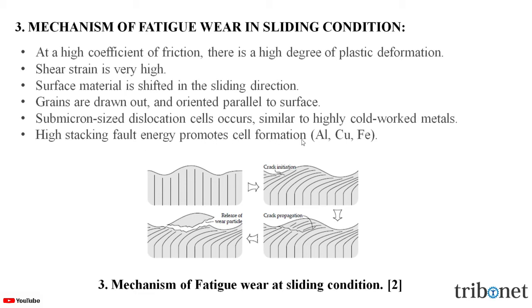Submicron-sized dislocation cells occur, similar to highly cold-worked metals. High stacking fault energy promotes cell formation in materials such as aluminum, copper, and iron. Here in this figure we can see the mechanism of fatigue wear in sliding condition, which is initiated by crack formation.